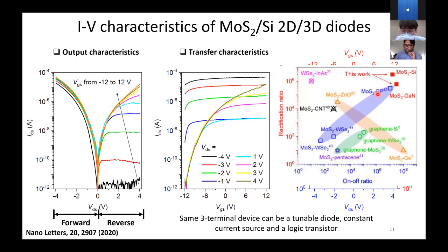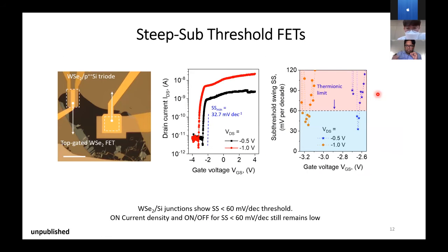And again, because of shortage of time, I'm not going into too much detail, but I want to show you some piece of unpublished data that we will soon be putting up online on arXiv. And that is, if you choose the right material, in this case WSe2, with p-type silicon and engineer the interface properly, you can get this heavily doped p-n heterojunction where you can modulate it strongly enough that you can get sub-60 millivolt per decade switching slope, right? So 60 millivolt per decade, this line over here, is supposed to be the thermal limit on which thermionic transport or thermally controlled transport occurs. If you are seeing switching below this value, or in other words, your slope is steep enough, then you are going to have tunneling currents happening, which is what we're seeing over here.